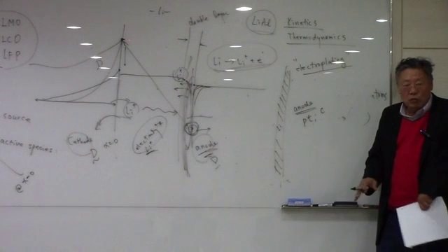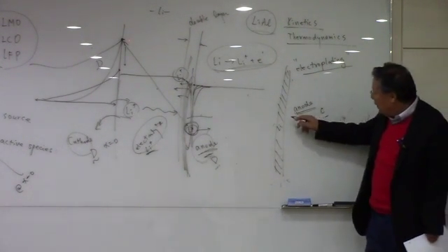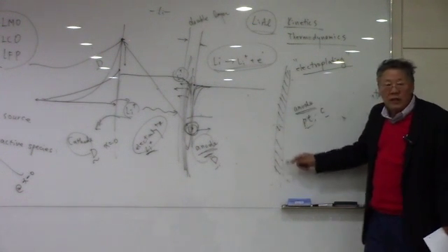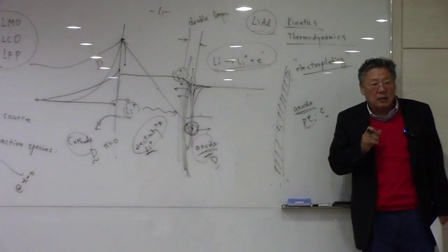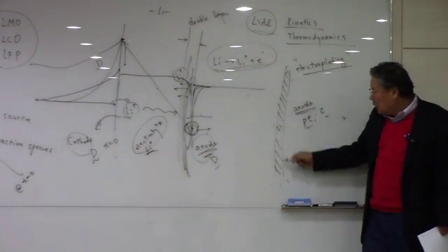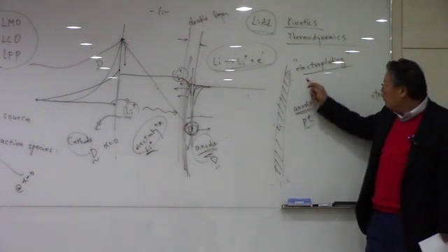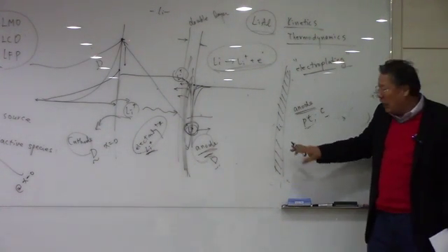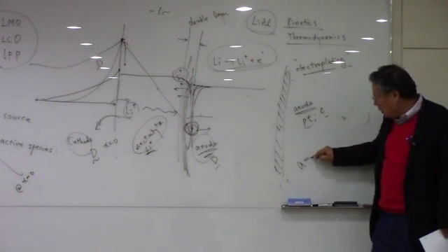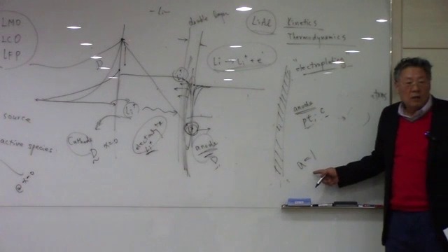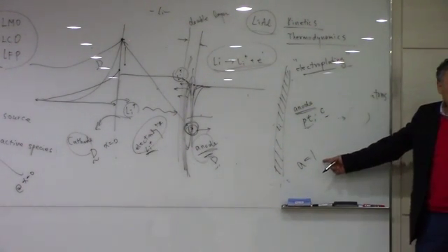And that is really true in the platinum or the graphite. Then the lithium will be accumulated at the surface. And if we have a good adhesion of this lithium to this substrate, then we call that electroplating, and the activity of the anode is just like the pure lithium; the activity is going to be 1. And that is good.